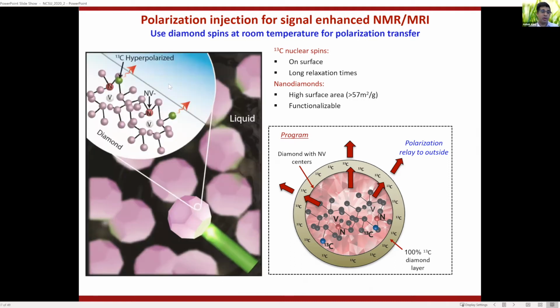So what we started to do was to try to envision this sort of cartoon, which is you have a bed of nanoparticles of diamond, you shine light on them, the NV centers polarize, and you transfer polarization to the carbon, and from the carbon to the outside world. I should lay out that this is a difficult problem because of very special features of these materials, and I'll go into more detail. But what we've been able to do so far is show that the carbons in the diamond can be very, very highly polarized, including on the surface. And now what we're trying to do is actually polarize materials with it.